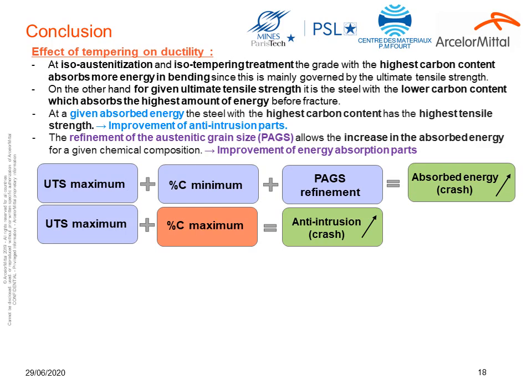If we are looking for the anti-intrusion parts, we need an ultimate tensile strength which is maximum and a carbon content which is maximum too. Bendability being a less important criterion on anti-intrusion parts than on energy absorption parts, the main characteristic targeted is the increase in tensile strength via carbon content addition.